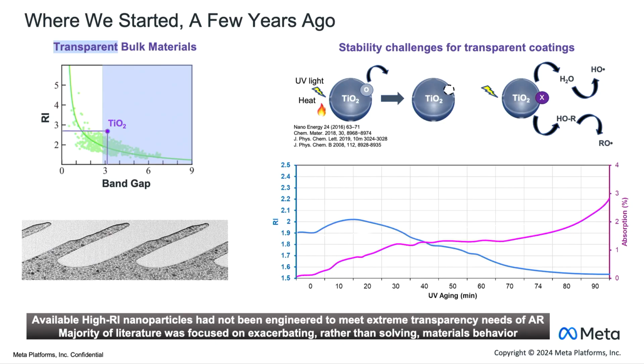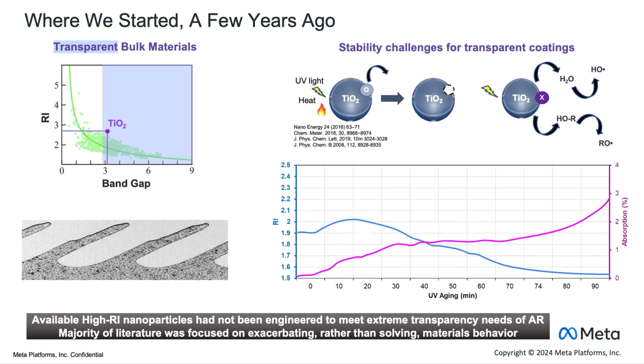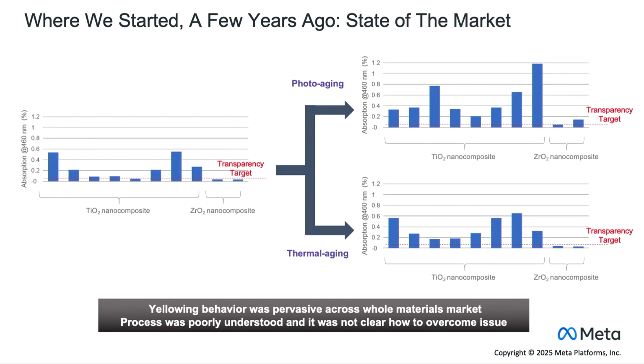But we also found the limitations very quickly too, right? And this is something very common in the field of AR. What we call a transparent material is very different from what most other people call a transparent material. We're asking for extreme transparency and extreme stability of the transparency over time. So titanium dioxide is also a very good photocatalyst, very good at degrading things around it, very good at turning things yellow. And even a trickle of this reactivity over time essentially completely degrades device performance, right? So what we found with a lot of these early efforts is that the refractive index goes down over time, goes back to maybe what an organic resin refractive index might be, and the absorption, yellowing, and scattering go up as well.